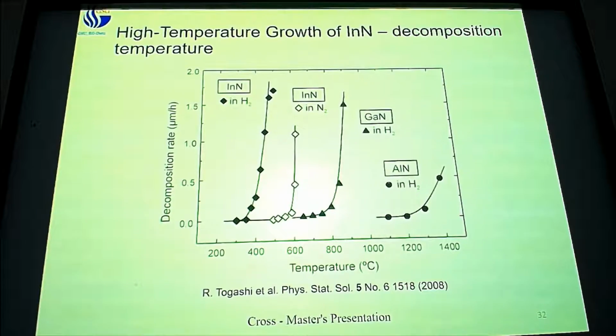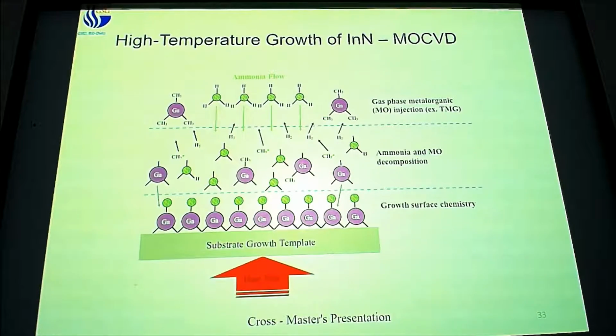So, how do we do that? Well, if we come back here, the graph I had at the beginning, if we set this at 1000 degrees Celsius to grow our gallium nitride, I can't put indium into the system. It will decay, it'll evaporate, it'll decompose before I get a chance to do anything with it.